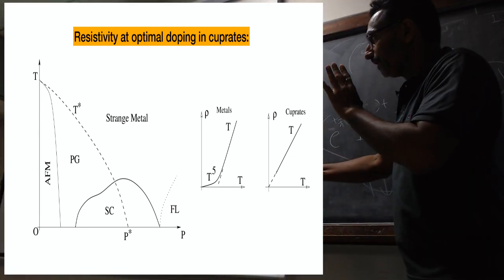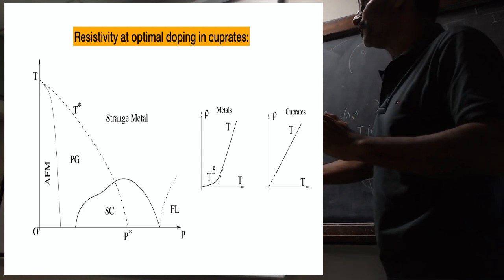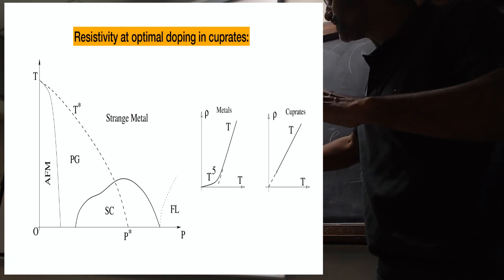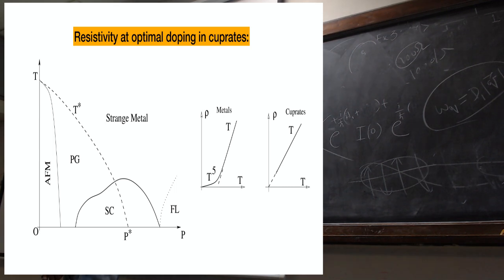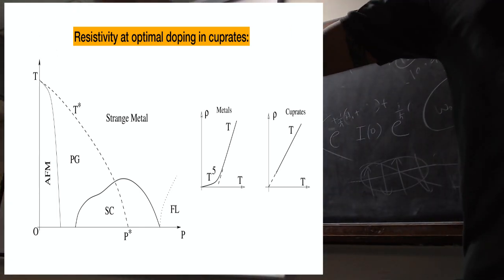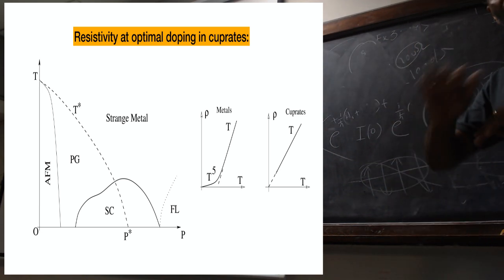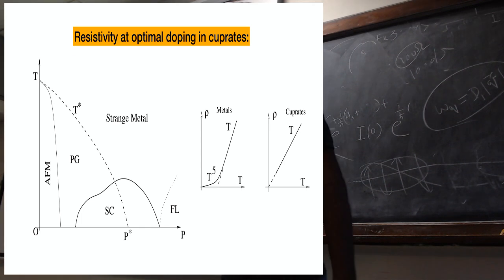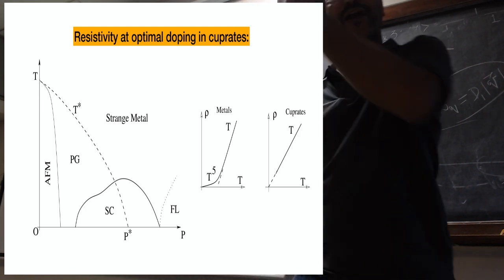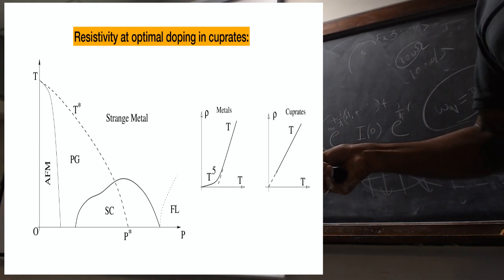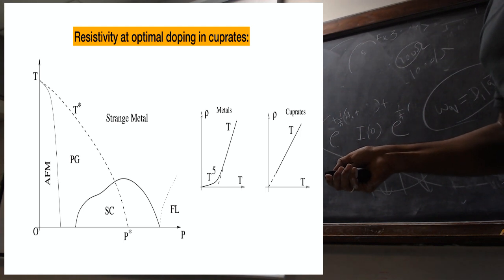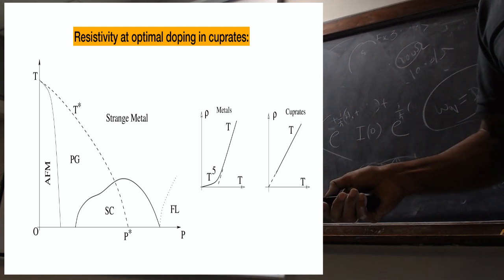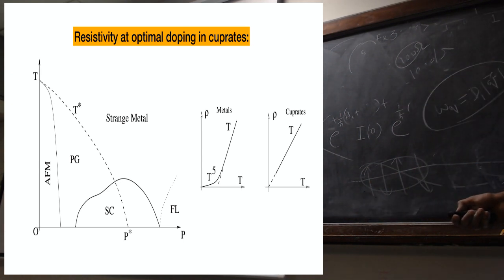Since there is no Curie temperature, there is no sharp magnetic transition. So these magnetic fluctuations exist throughout the phase diagram. But once you go below this point here, there is an infinitely long range antiferromagnetic order, then those fluctuations don't exist, and you can think of magnons in this region. But we are far away from the magnetic region. That's the whole trouble people have been fighting with for cuprates, because it's not a Fermi liquid. It is not a magnet. It is not a Fermi liquid with lots of magnetic fluctuations. How do you deal with this problem? So that is why you describe these somewhat shorter range correlations.